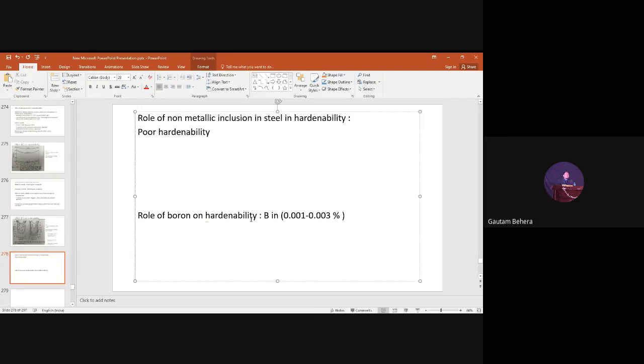And the second one is the role of boron on hardenability. Actually, if boron is present in very small amounts, hardenability will increase. Why? Because the boron gets dissolved into the austenite phase, and it segregates along grain boundaries. So this boron, when added in a small amount, becomes soluble in the austenite phase and segregates along the grain boundaries.